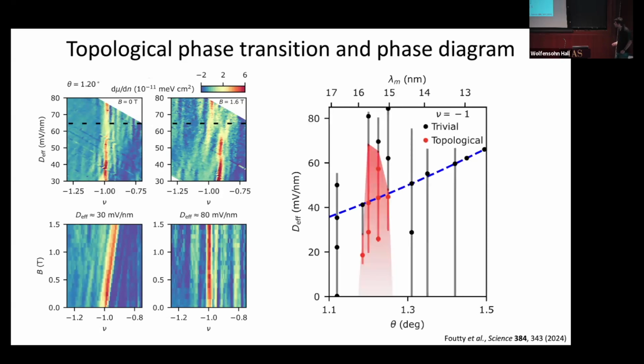All right, good. So building up these same sorts of measurements taken now in different locations and at different displacement fields, we can build a full phase diagram of where you get a trivial ground state and where you get a topological ground state as a function of twist angle and displacement field. And so you can see there's this narrow dome of topology that occurs right around 1.2 to 1.5 degrees or so.